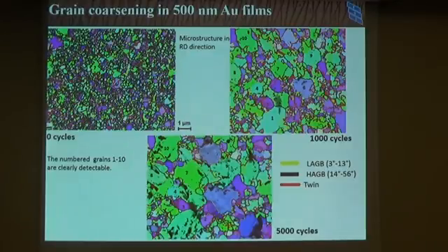But the next question is, what is so special about those grains? There must be a reason why these grains coarsen and others do not. And then we tried to look, of course, at the grain orientation, for example, because you can have grains which are oriented with respect to the loading direction so that they have, for example, a high Schmidt factor or a low Taylor factor or low Young's modulus or whatever, but we have not found any correlation between the coarsened grains and their orientation.